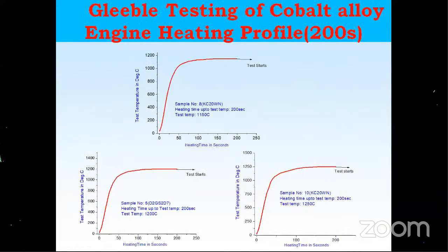So what we found is that the high temperature alloy which we have used is a cobalt alloy, and initially we had done at 1150 degrees centigrade. That's the maximum temperature we expect in our normal operation. Then we had done at 1200 degrees, which is margin. Again, 1250, 100 degree margin. Even every 10 degree margin is very, very important. And what we do is, within 10 seconds, I reach this temperature, and I keep it for the entire mission period of 200 seconds. Then I test it. That means after exposure only, I've taken the worst case of testing.